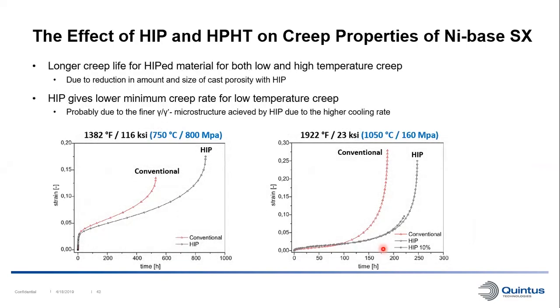And here we see the results of the creep properties. So they tested two different conditions, one with a lower temperature and higher stress, and one with a higher temperature and lower stress. And in both cases here, we can see that the HIP variant has a longer creep life than the conventional heat-treated variant. And this is due to the elimination of the cast porosity in that material.